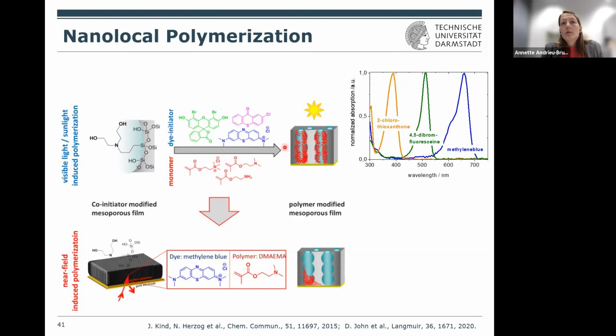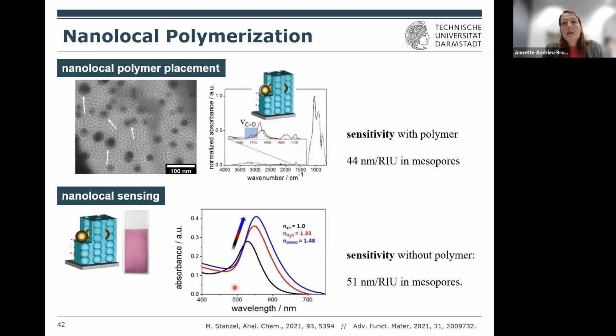So a versatile mechanism again, and this was again taken from the work of Zouheir, are dye-sensitized polymerizations. And they are not very much controlled from the perspective of a polymer chemist, but they are very versatile because you can perform them with different monomers, and you have dyes of almost any wavelength in the visible range to go really even to 600, 700 nanometers for polymerization initiation. And this works actually quite well.